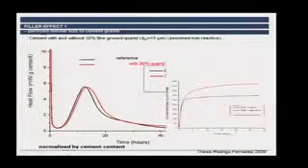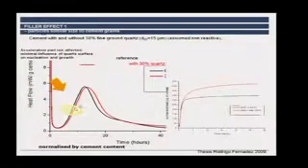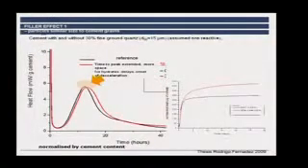And what we see here, these are results from calorimeter output. So this is the heat flow, this is the rate of heat evolution, and this is the cumulative heat evolution. So this is like the rate of reaction, this is like the overall amount of reaction. And in terms of the rate of reaction, you can see that we've got very, very little effect on this first slope here, this first bit of reaction of the Portland cement, but that this reaction seems to go on a bit longer after the peak. And we're pretty sure that that prolongation of the reaction, the time extended, is because there's actually more space.